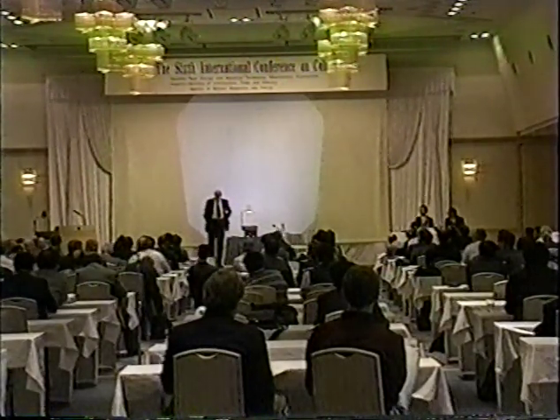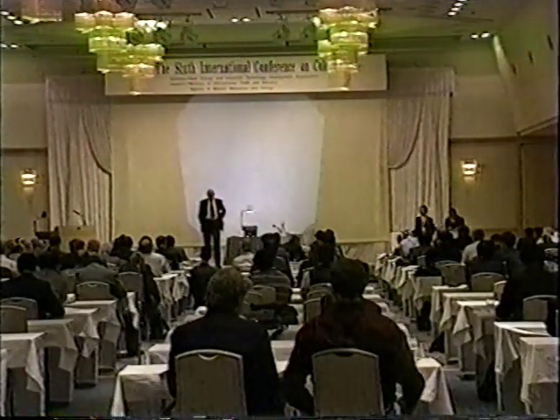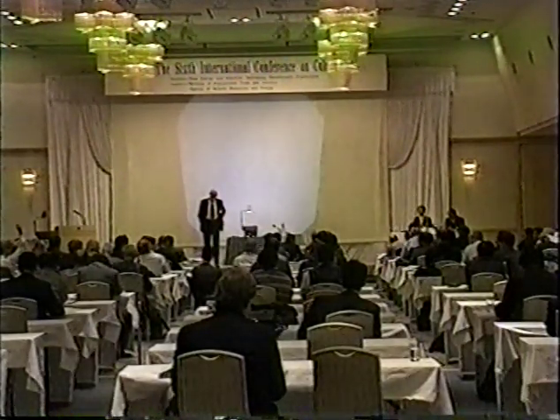Dr. Dash? Are you planning to cross-check by any other technique? Well, there aren't many other techniques that will see the whole sample, but for example, boron-10 doesn't produce any radioactivity, and so I can't do it by neutron activation. I could, of course, try to do it by the surface analysis methods, the time-of-flight SIMS, and I have started to try to do that, but I'm always nervous that I'm hitting an inactive spot on the sample, and that it would take too long and too expensive to finally march my way all over the sample to be sure. How much of the surface does the SIMS scan? Well, you can have it be about 40 or 50 microns at a time, I guess. I don't do the work myself, but the model that does the work for me scans 3 millimeters. 3 by 3 millimeters. Well, I guess it can be done, that's true.